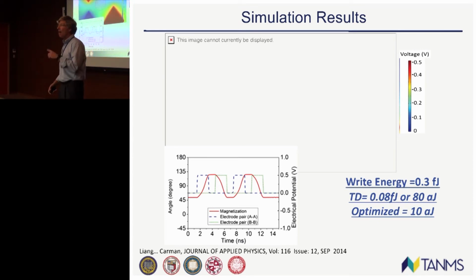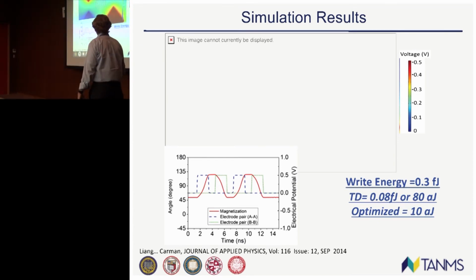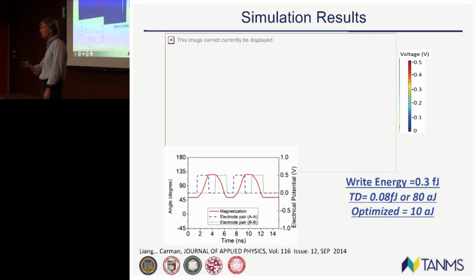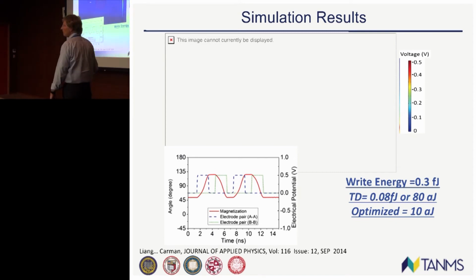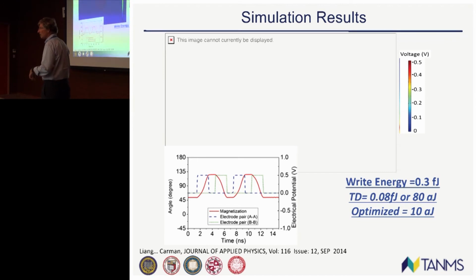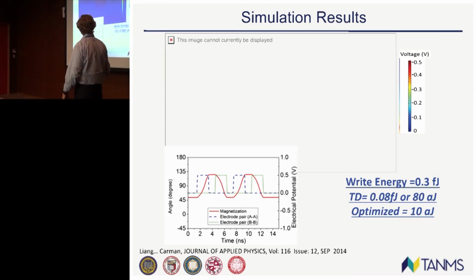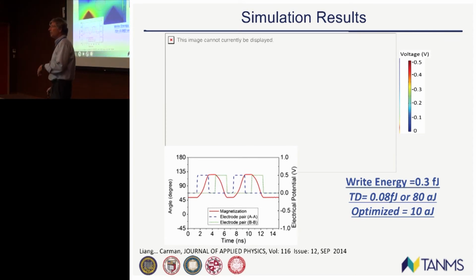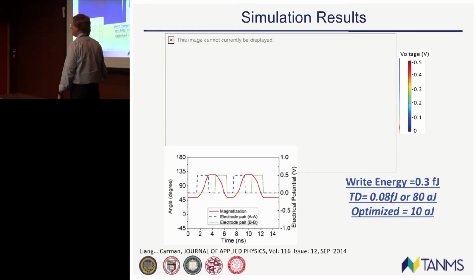And now let's say, how much energy does it take? Well, the energy of this specific system you're seeing in front of you is about 0.3 femtojoules. So that's better than anything we've had, but it's still not 1 attojoule. You may say, well, Greg, why aren't you at 1 attojoule yet? Well, the reason we're not at 1 attojoule is because it's nickel. If you go to Terfenol-D, which is the best magneto-elastic material out there, now all of a sudden it's at 0.08 femtojoules, or 80 attojoules. You say, well, why aren't you down lower than that? You have to optimize the system. If you optimize the system, it's down to 10 attojoules.